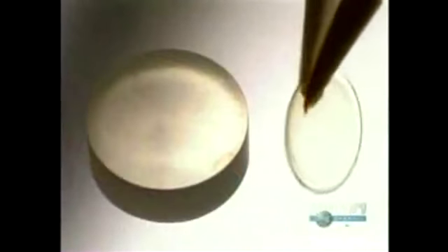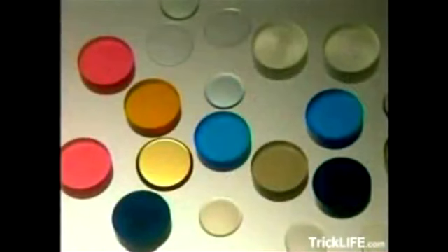This little vial that we might find at optometrists is sealed with a silicone cap and another of aluminum. These vials are placed in a sterilizer at temperatures of 250 degrees Fahrenheit for an hour and a half. The contents will remain sterile for up to 7 years if not opened. The production of a lens involves 14 steps. If we exclude the rather lengthy hydration process, actual lens production requires only 15 minutes. They can produce almost 1,000 contact lenses per day, all made from these tiny colored discs.